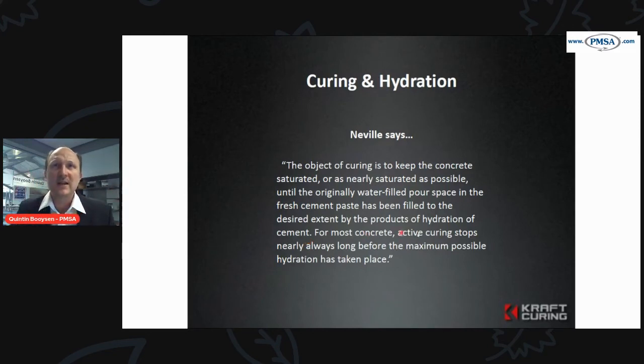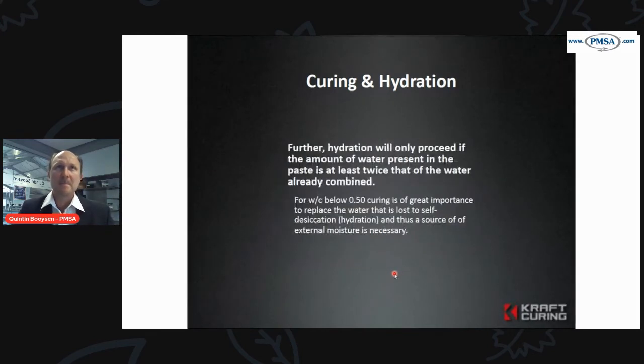For most concrete, active curing stops nearly always long before the maximum possible hydration has taken place. So what do we mean by that? Most concrete is allowed to kind of dry out. We've taken away the presence of water by not properly wrapping, not properly having a curing environment, and your cement is just not allowed to hydrate fully. And that means you've essentially wasted cement in your production of your concrete or in your concrete product.